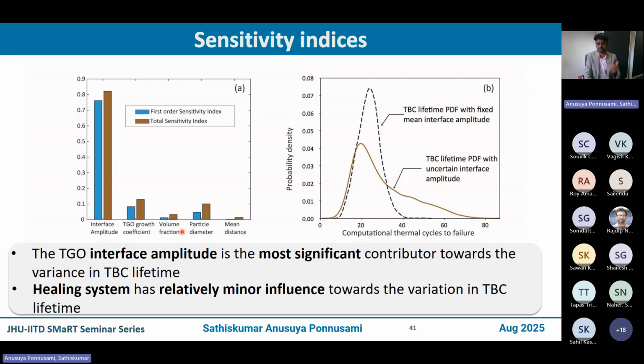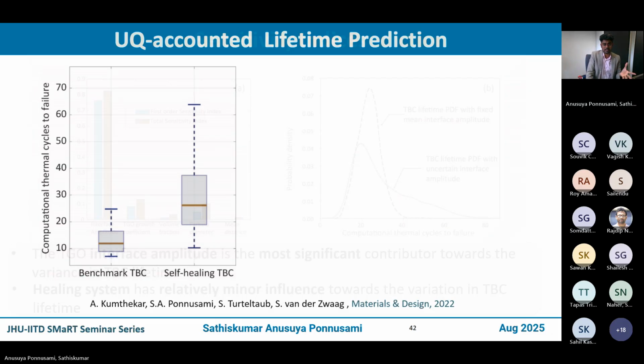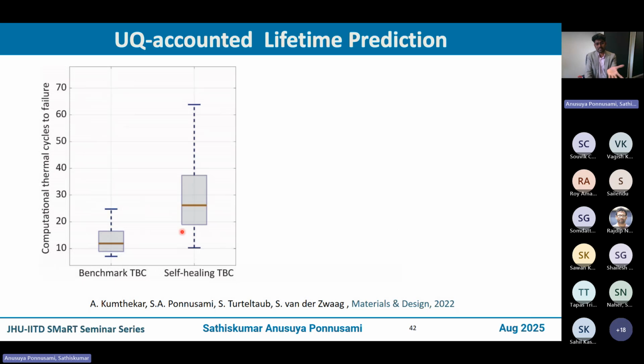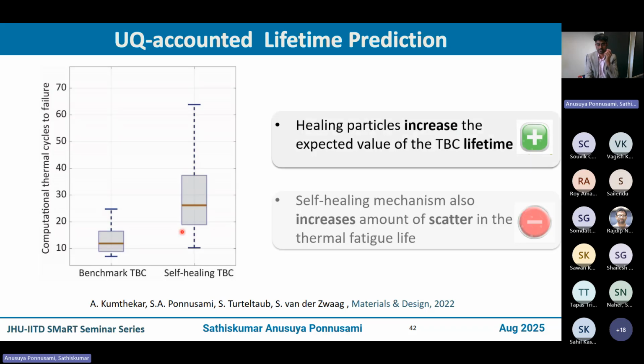On the right, you have the PDF function for the lifetime. Of course, the PDF gets broader when you have this uncertainty included. So to quickly summarize, you clearly see self-healing improves the lifetime, but with a large scatter. And that is where these surrogate models can come in handy to quantify the uncertainties and give some useful insights to the material scientist. So that's the second example that we saw.